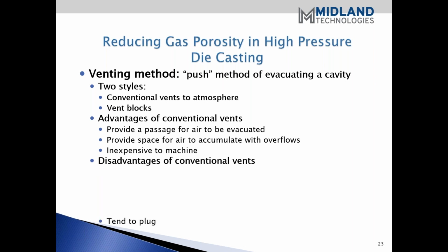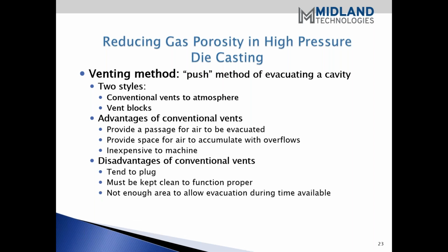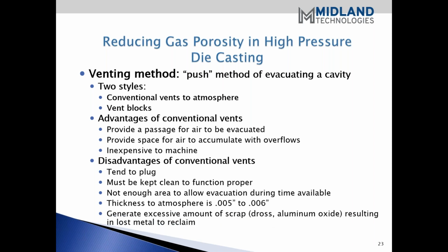But some of the disadvantages of conventional vents are that they tend to plug up. They're not very thick, only about 5 mils, 0.005 inches. They must be kept clean to function properly, and there's not enough area to allow evacuation during the time available. So you do need quite a few vents coming out of your die, depending on the size of the mold you're making, and sometimes it doesn't allow you enough time to evacuate the area, depending on your real estate and such. Again, the thickness to the atmosphere is only 0.005, 0.006, so it's not very big. They also generate an excessive amount of scrap, resulting in lost metal to reclaim. So that's the first type of push method.